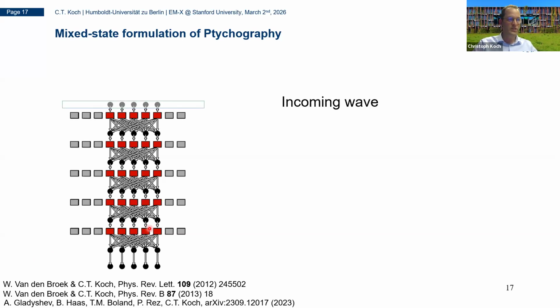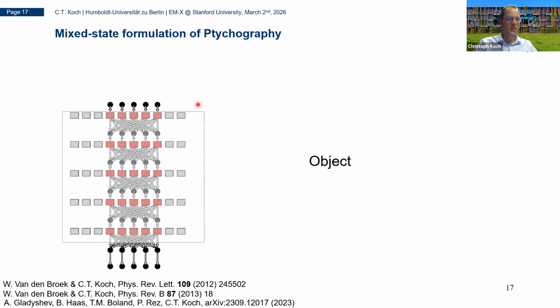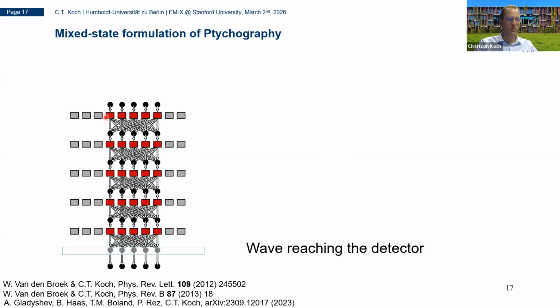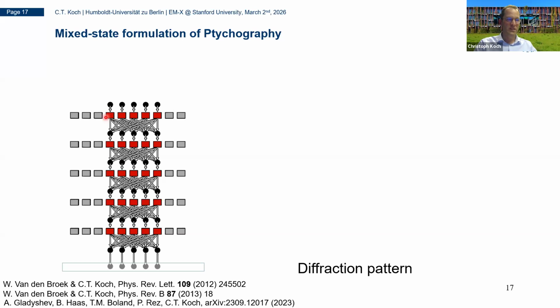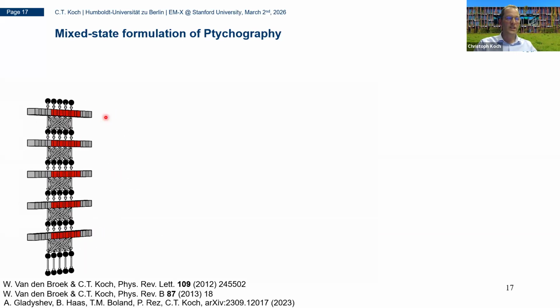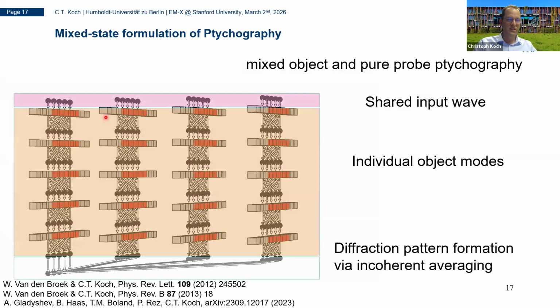So you have this incoming wave, which you can treat basically as the input layer in this neural network. And the object then has these different weights, which are the potential voxels in the 3D potential of your object. And then, of course, you have a wave that comes out at the bottom of your sample, and you then compute the diffraction pattern from that by taking the Fourier transform and squaring the amplitudes. Well, if you now want to simulate this thermal diffuse scattering, or include the thermal diffuse scattering into your ptychographic reconstruction, you need to have multiple objects, not just one, because one would only be able to have one configuration of atoms.